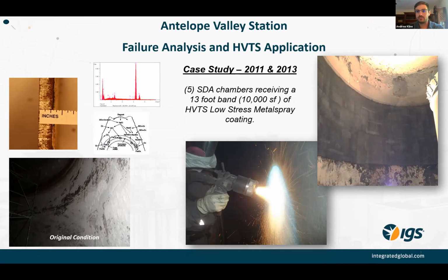So another situation where it was a similar corrosion issue in the spray affected zone of the Antelope Valley SDA units. They were experiencing wall thickness loss. They knew they were having the failures, and they wanted to freeze the condition before it got worse. So they turned to IGS in 2011. Well, I guess turned to us before that, and worked with us to take samples of the failed material, work with our lab, analyze what was going on, what was causing the corrosion, and then develop a HVTS solution specific for that application. And it was installed in 5 of their chambers in 2011, and then 5 of the chambers of the other unit in 2013. And you can see the application photos and then the photo of the new application there.